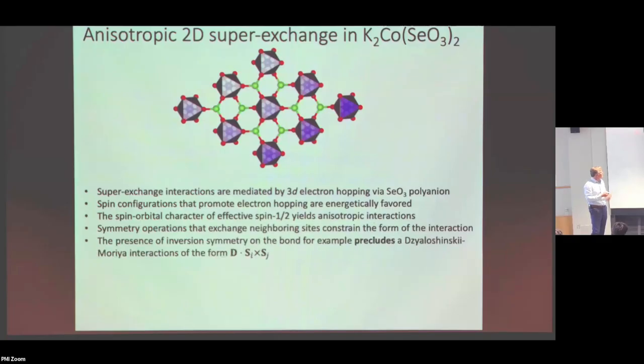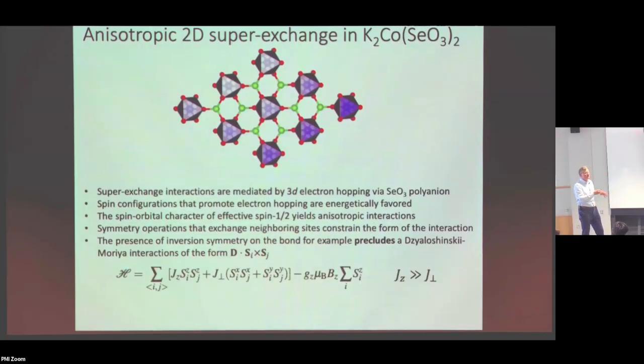There could also be a DM interaction, now that we have spin-orbit interactions, but because this selenide polyanion is so planar, it actually builds a structure that has a mirror plane, and that mirror plane really extinguishes the DM interaction. So I don't have that one, and so you end up with exactly the kind of Hamiltonian that we are interested in. It has the Ising term, it's Wannier-type frustrated, and then it also has a little bit of this transverse interaction, and that will throw in quantum fluctuations, which can lift the degeneracy of this Wannier manifold.